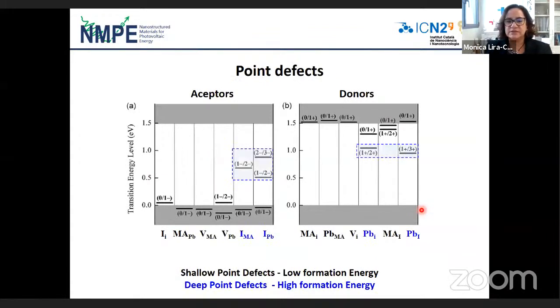Here you can see some deep point defects that have high formation energy. Some examples of these deep trap defects are, for example, under-coordinated halides or lead. And those that are shallow point defects with low formation energy are, for example, iodine or methylammonium, which we all know are the most mobile ions in this halide perovskite.